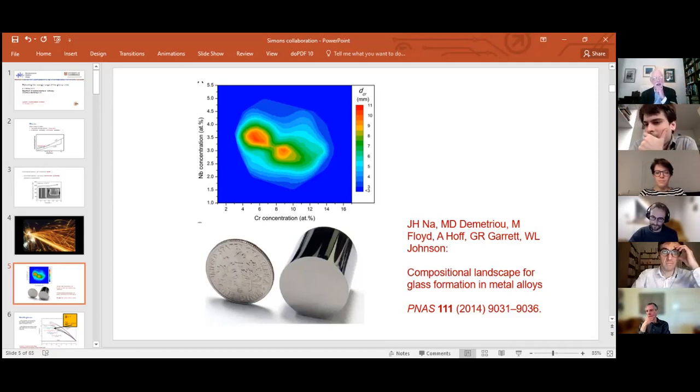It would be interesting to think about how far you could go in even more extreme rejuvenation. And I suspect that we are pretty close to some sort of limit beyond which the glass would simply not be stable. It would crystallize. And we know for sure that you can induce crystallization without temperature rise. You can induce crystallization by mechanical deformation of the glasses. So I think that's the limit we're up against. But I don't think we've softened them so much that they are now softer than what would have been the comparable engineering materials. Okay, thank you very much.